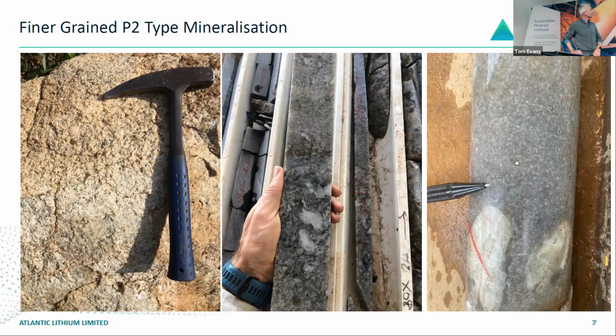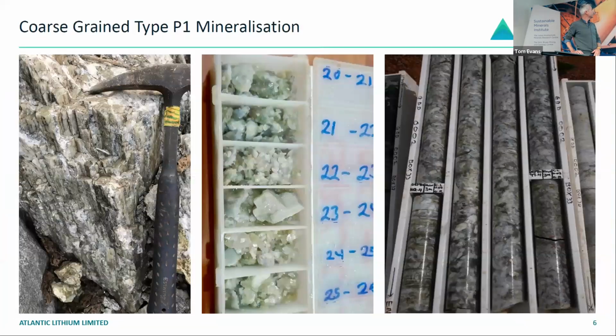So the grade of this material here is around 1.2 up to 2% lithium oxide, as is the grade in this material. So this would probably be high grade, probably around 2% lithium oxide. And then once it's concentrated, you'll get to that 6% concentrate value. It's amazing to see how that grain size variation, these are all just very fine spodumene crystals, gives that same overall resource grade of 1.25.